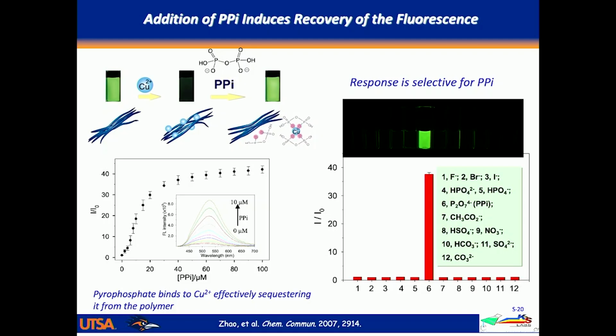But then what he showed is that if you add pyrophosphate, this negatively charged phosphate ion, you can quantitatively recover the fluorescence of the polyelectrolyte. And what's happening in this case is that copper is being sequestered by the pyrophosphate. The pyrophosphate is acting like EDTA. It's sequestering the metal ions, and it takes them away from the polymer, and that causes the fluorescence to recover. So it's basically reversing that binding effect that I mentioned previously.